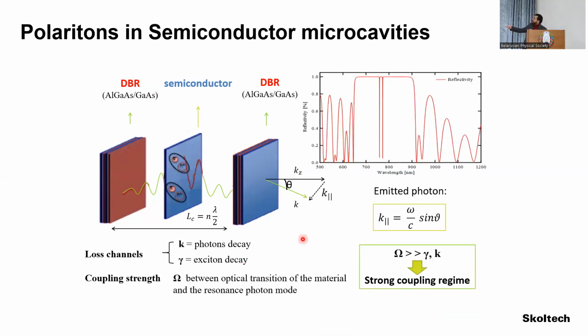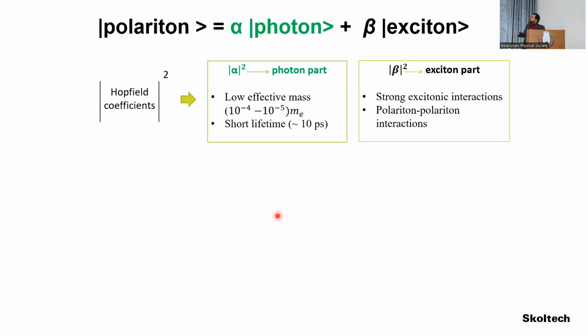And if I look now at the reflectivity from this structure, instead of just looking at the bare cavity mode, I see two reflectivity minima. These are like the two solutions of two coupled pendulums. These are the new normal modes of the structure, which we call polaritons. Going yet one step deeper inside, I can therefore describe the polariton as an admixture of a photon and an